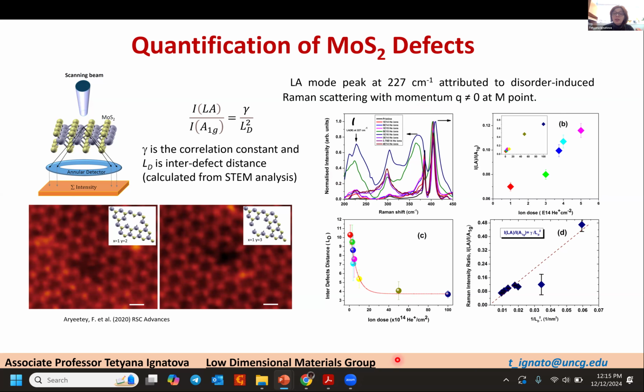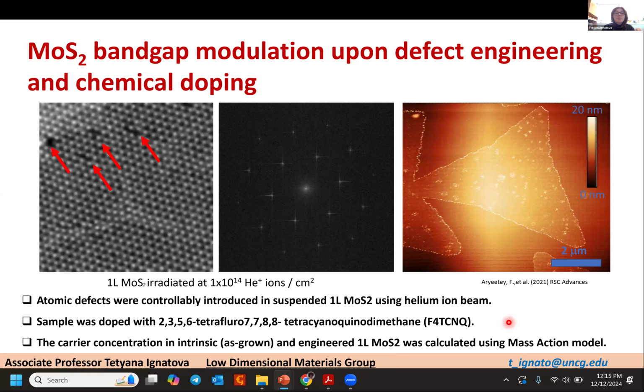Then we combined Raman characterization and our analysis of STEM data, and we extracted and calculated the correlation constant, which appears to be in linear correlation with Raman data. With this knowledge, we can do MoS2 band gap modulation, when we purposely introduce defects and combine it with chemical doping.